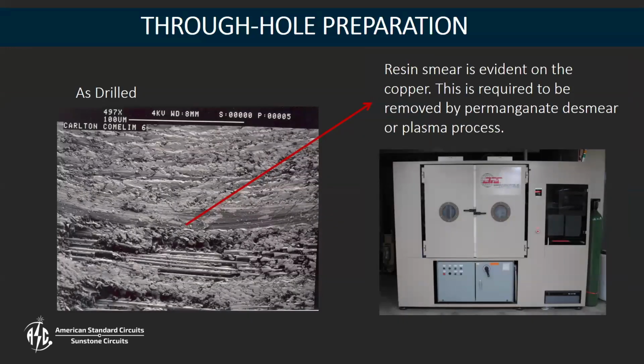All right, so during that drilling process, drilling has friction and creates heat, and epoxy is kind of a plastic, and it tends to melt under heat a little bit. So what happens is you get a smear of that resin as you're drilling through the process. It tends to coat your internal connections and is not going to create a robust connection between your through hole and your internal post. So either a chemical process or a plasma process is employed at this part to dissolve that melted epoxy over the internal layer posts. Does a great job. It creates your etch back if needed, etc.